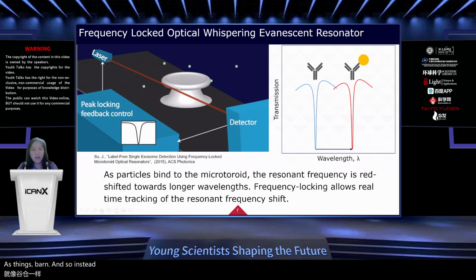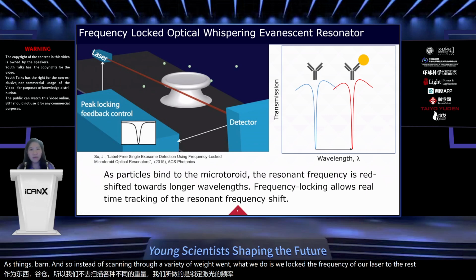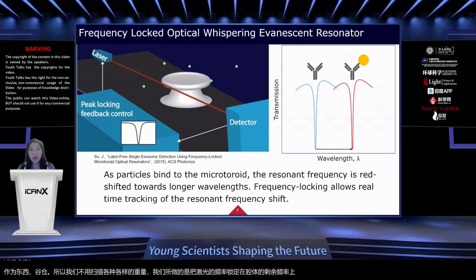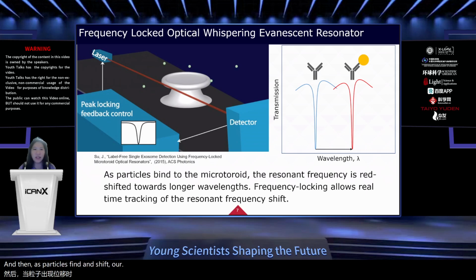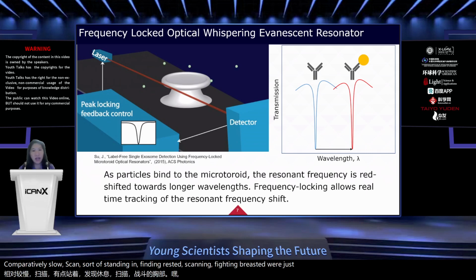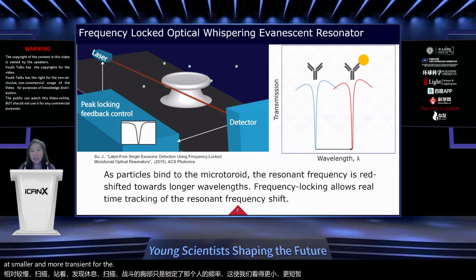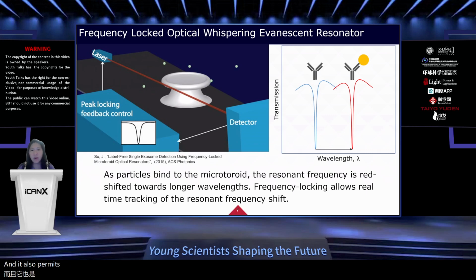And so instead of scanning through a variety of wavelengths, what we do is we lock the frequency of our laser to the resonance frequency of our cavity. Then as particles bind and shift our cavity frequency, we measure the amount of voltage our laser controller has to apply to follow that event. This enables us to do real-time tracking. Instead of doing this comparatively slow scan, because instead of scanning and finding resonance we're just locked to that resonance frequency, we can look at smaller and more transient events. It also permits more averaging of our data.